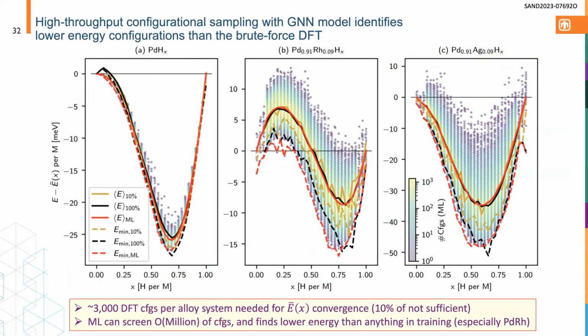So this slide's a bit busy to get into too much of the details, but I wanted to emphasize that in order to do the thermodynamic predictions, you need to be able to screen tens of thousands of configurations. So this color-coded density in the back is essentially all the machine learning predictions. And the solid lines in the middle are the average of those formation energies as a function of hydrogen content.